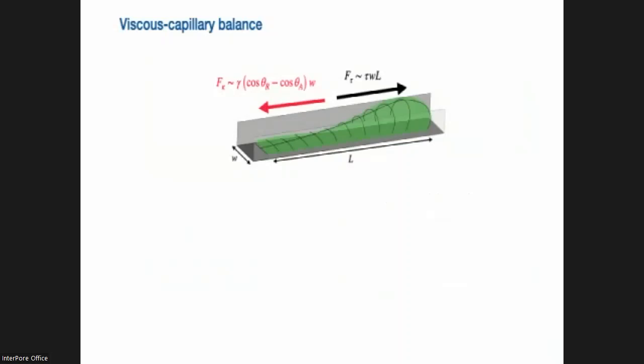So the question is, what kind of droplets can we resist? How long can they be? Because we can see here that the shear stress increases with the length. So the longer the shear stress force, the force increases with the length. So there should be a critical length for which we can retain droplets, for which the pinning force is sufficiently large to resist the shear stress force. So we can define that by just balancing these two terms as this expression here. We have the surface tension over the shear stress multiplied by the contact angle hysteresis.